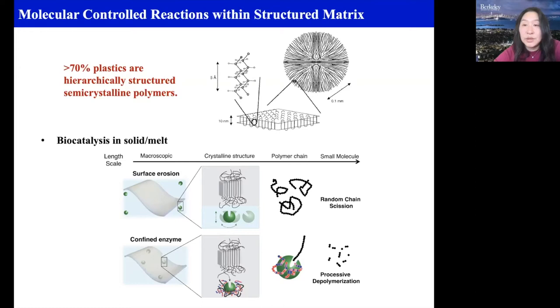And also because the enzyme happens to be in the amorphous domain, that's where the polymer chain ends can be. So that opens up the opportunity for a processive depolymerization from the chain end. You basically eat it at the chain end rather than by random transection. Random transection can break it down into small pieces and it really accelerates the formation of microplastic. It doesn't really eliminate microplastic, but processive depolymerization does.